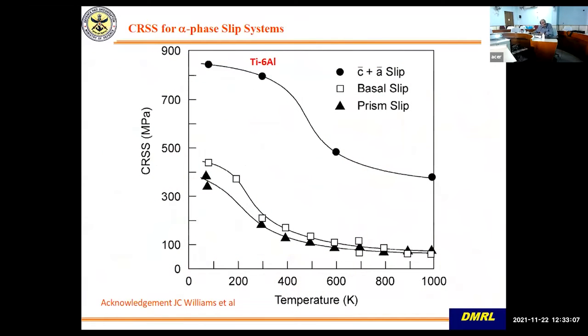Now, in order to explain that phenomenon, I am just showing you this critical resolved shear stress in a Ti6Al crystal as a function of temperature. This shows you the stress required to move the dislocation. So here these are different slip systems. This is prism slip. This is for basal slip. I had shown you the hexagonal crystal structure, which if you remember. So this is prism slip, this is basal slip, slight difference, not much.